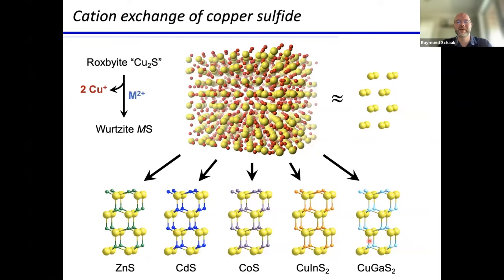And one of the really important aspects of this chemical transformation process is that crystal structure is often retained. I'm a solid state chemist, and so I love looking at crystal structures. When I look at this crazy crystal structure of copper sulfide, my brain, without even trying, simplifies some of the craziness to make it a little easier to understand. The sulfur atoms that are in yellow here simplify to a hexagonal close packed crystal structure, so an AB stacking sequence. For the most part, when you do cation exchange in these systems, barring any other issues, and there are cases where this doesn't hold true, you essentially keep that AB hexagonal close packed stacking of the anions, and you can get the wurtzite forms of zinc sulfide, cadmium sulfide, cobalt sulfide, copper-indium sulfide, copper-gallium sulfide, and many others. And that gives you a crystal structure picture of what we're talking about here.